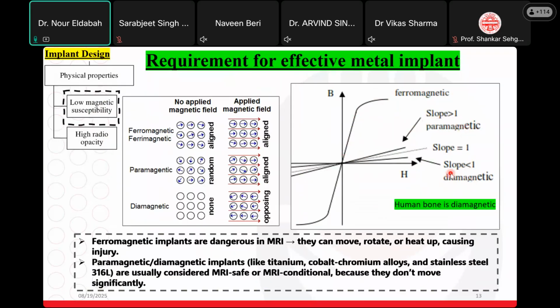However, for paramagnetic or diamagnetic, the difference is just in the direction of the magnetic dipole of the material, and we can know from the vibrating sample magnetometer magnetization curve: if the slope of the linear fitting of the magnetic curve is lower than 1, it is diamagnetic, or higher than 1, it is paramagnetic. Considering that our human bone or human tissue is a diamagnetic material, going to a diamagnetic material is better and most preferable to avoid severe accidents that may be caused by the magnetic field of the MRI.